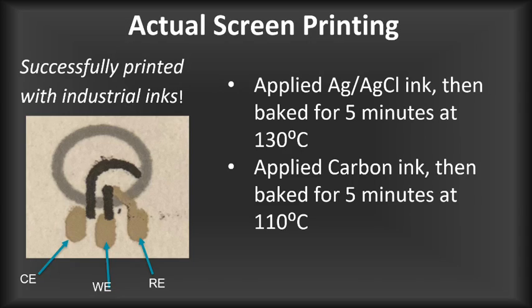And so, following the previous steps, we then applied the silver chloride ink. I actually got a little on me. It's pretty irritating, so make sure to wear standard lab safety gear when using this. Then we baked in an oven in a fume hood for 5 minutes at 130 degrees Celsius. We then applied the carbon ink, baked for 5 minutes at 110 degrees Celsius. And again, this must be done in a fume hood.